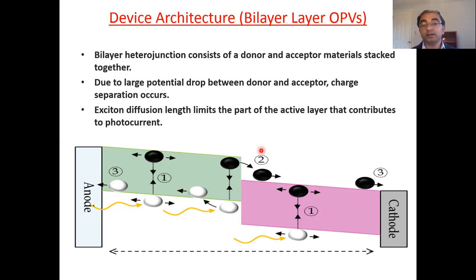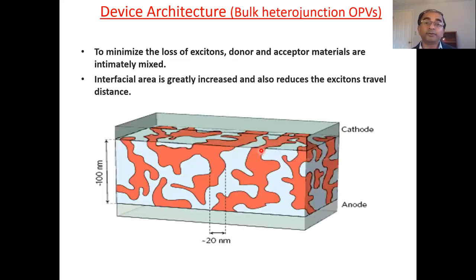So we have to think in a different manner. And now comes the bulk heterojunction solar cell. What is that? In this bulk heterojunction, we mix two materials, one donor and one acceptor. The beauty of this structure is that we have junctions everywhere. You can see from here, this red part is one material, and this whitish part is another material. And there's a junction everywhere. When light is incident, a lot of electron hole pairs are generated, and they are dissociated at the junction. And then they start their journey towards their respective electrodes. From here, the diffusion distance is very, very less, and you have a more collection efficiency from this, and hence you will get a very high efficiency by these bulk heterojunction solar cells.